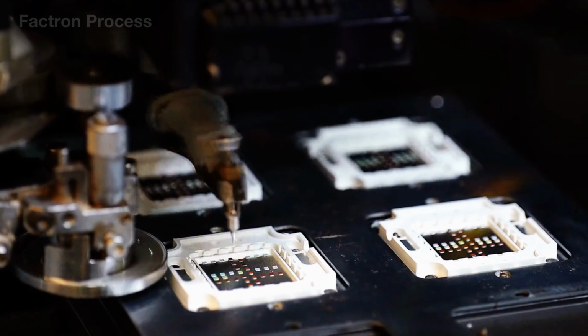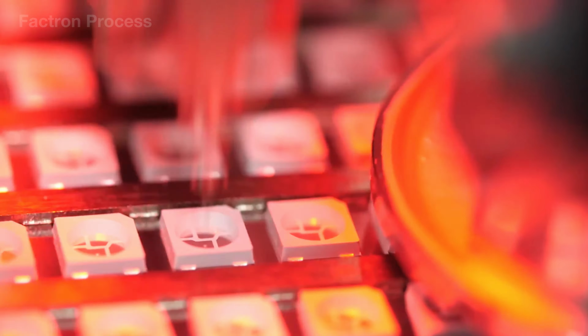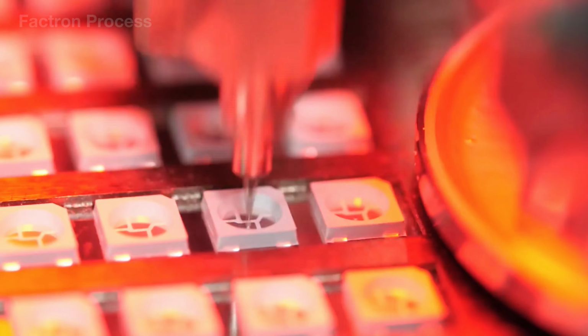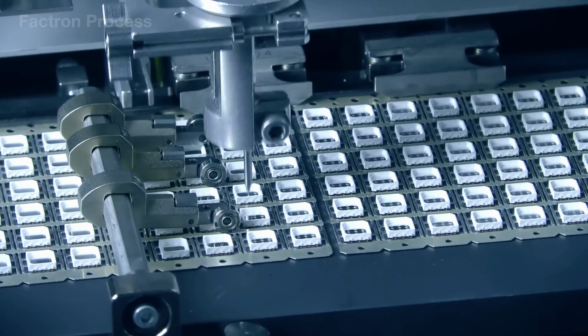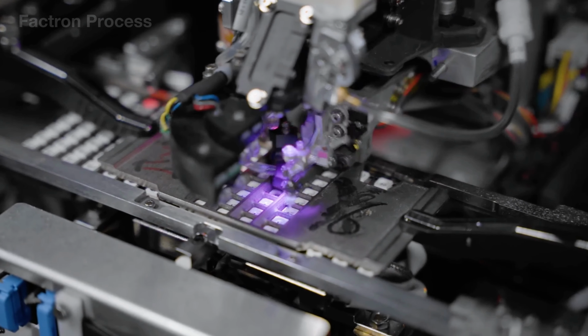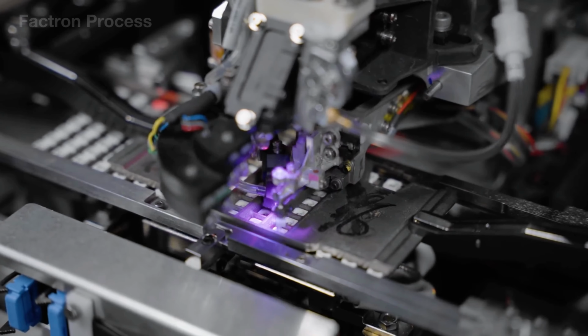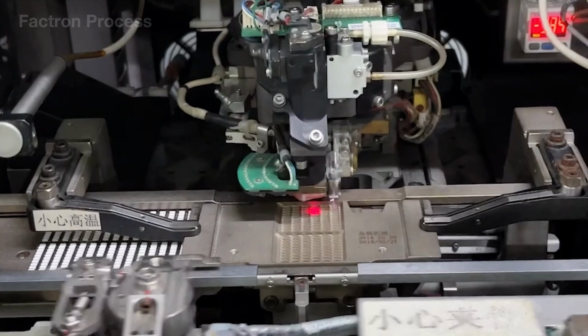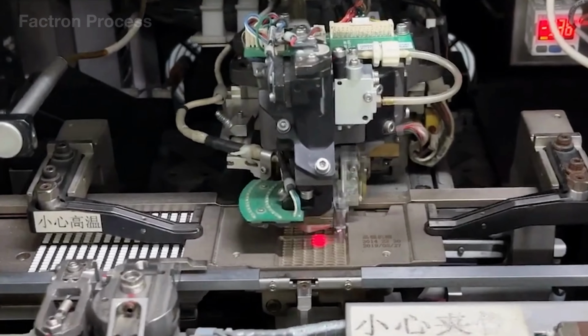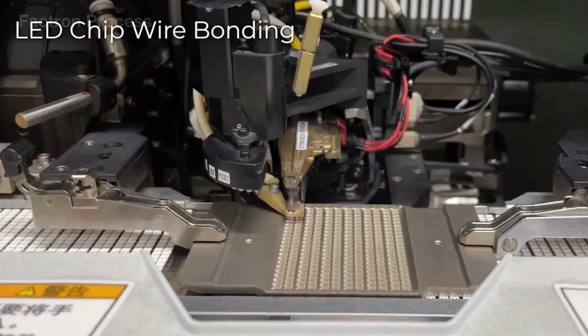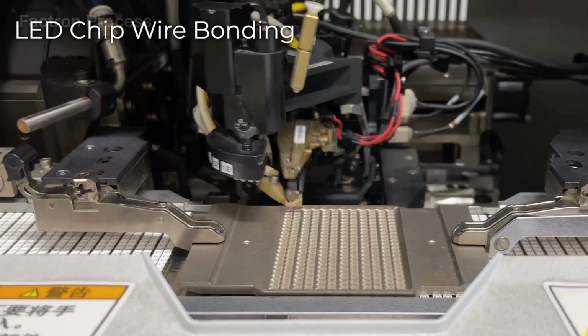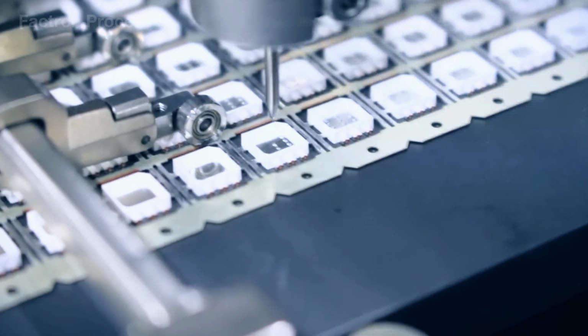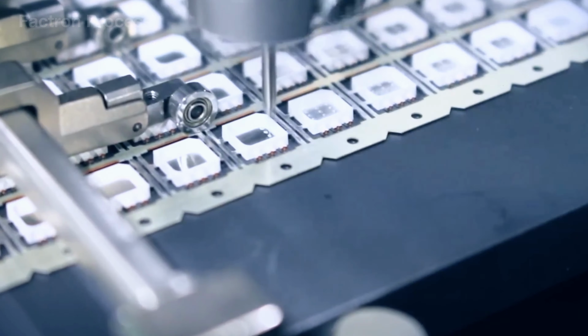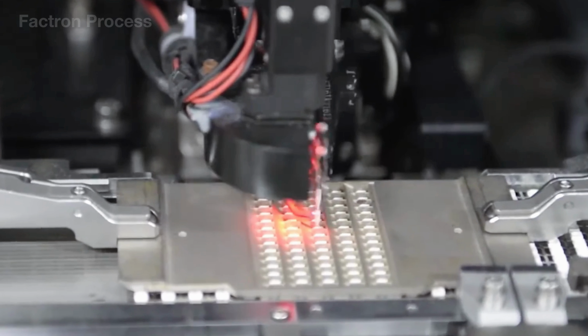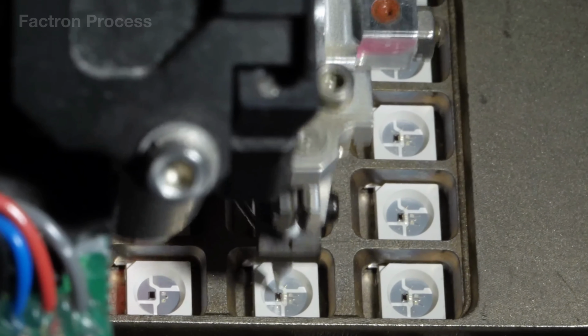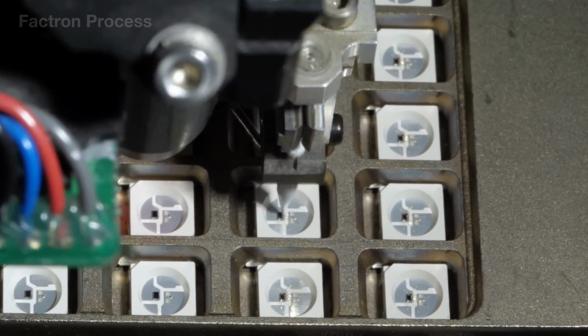The machine's bonding tool lowers onto the chip and combines heat, pressure, and ultrasonic vibration to attach the end of the wire firmly to the electrode. The wire is then drawn into a small arch before its other end is bonded to the package. The entire operation takes only a fraction of a second, but the required precision is extremely high. A single weak bond, an overly tight wire, or an incorrect loop height can cause the LED to flicker, shorten its service life, or stop emitting light altogether.